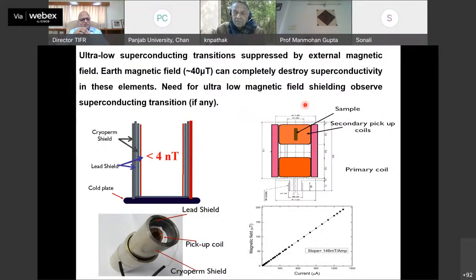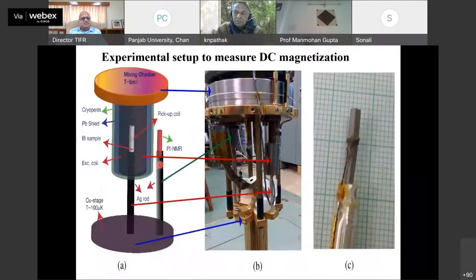So we decided to build a chamber which is a mixture of Cryoperm and superconductor. Superconductor is also a very good shield because it expels the magnetic field. So we made a chamber combining this Cryoperm, which has a very high permeability even at 4.2 K. So several layers, and then we measure this field, which is 4 nanotesla. So it's much smaller than the Earth's magnetic field. So that is the chamber in which we are looking for the superconductivity.